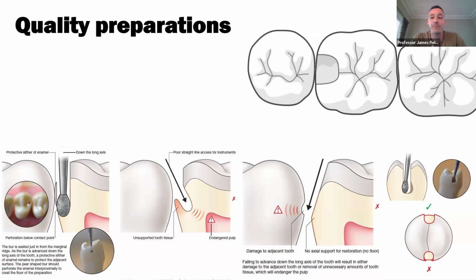Believe it or not, it's something which a lot of people are still quite hesitant to do. A classic class 2, as we used to refer to them, the posterior approximal box needs to do certain things. And if it doesn't, then it causes problems. So, it has to clear the contact point. Contact point just below it is the area of stagnation, and it's the area where that carious process is most likely to begin. It's the area on your radiographs where you will see that radiolucency starting to its way through that thickness of enamel, and in the end, punching through to start to infiltrate the dentine underneath. We see lots of situations where people don't clear the contact point, and we get recurrent caries. So it's really important that we do that.